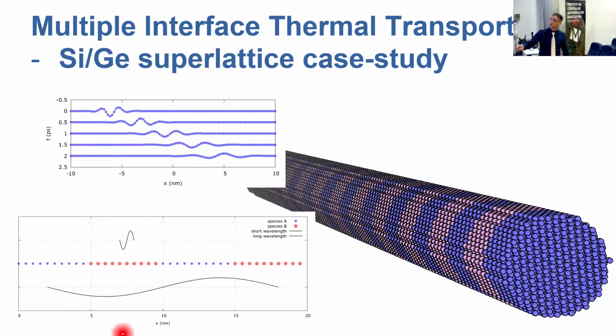Now, if you look at this, it is pretty clear that a long wavelength phonon, so an excitation like the bottom one, will experience just a sort of average material with average properties and will be completely insensitive to the interface structure. Whereas an excitation like this one will experience a sequence of interfaces along its path. These two different excitations would travel in a very different way inside the material. This can be seen in the temperature profile of the superlattice.